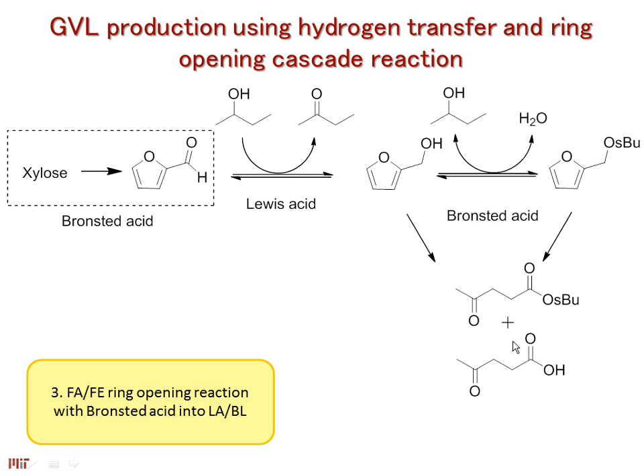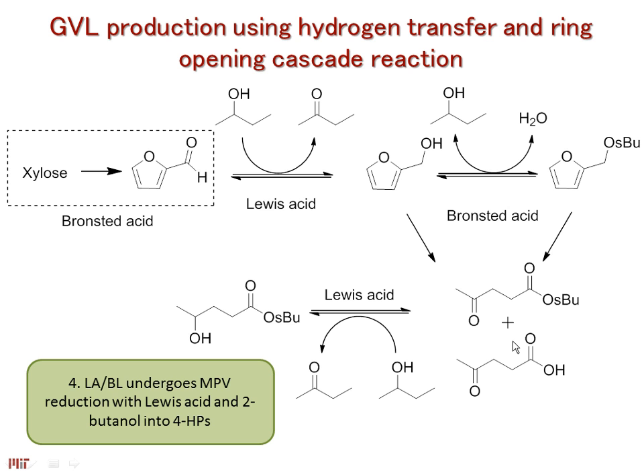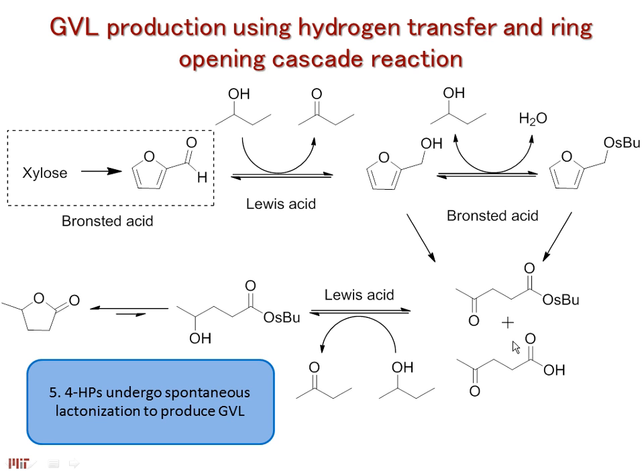This can then undergo esterification chemistry also in the Lewis acid site. You can then open up the ring with a Bronsted acid catalyst to make a levulinate derivative. And from there, you can imagine you can do a second transfer hydrogenation step where you create the pentanoate, and that will spontaneously lactonize to GVL. So that was our thinking of how we could couple perhaps a Bronsted and Lewis acid catalyst to go all the way from our sugar to our GVL without using molecular hydrogen or high pressures of molecular hydrogen.